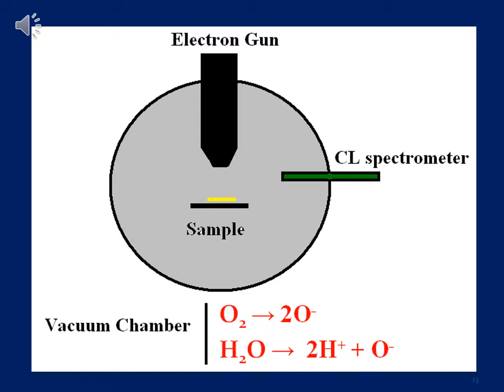And the way we went about it was to take a sample, put it inside a vacuum chamber, then mount a CL spectrometer onto the chamber so that we can monitor the CL intensity changes upon exposing our sample to a prolonged electron beam. Now, we know that in our chamber we have oxygen, which we will also have in real environments. We have water vapor as well. What we then went on to do was backfill oxygen, putting an oxygen feeder next to the sample so that we can have an electron beam interacting with the oxygen and splitting it from oxygen molecules to atomic oxygen species, which are very reactive so that they can attack the surface. In so doing, we are rapidly aging our material.